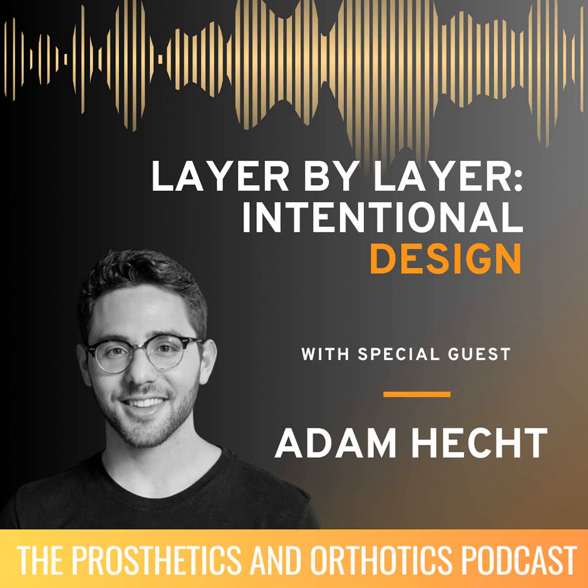Yeah, absolutely. I mean, the Filament Innovations machine is a great starting point. It's almost like a gateway drug to a larger format and printing with pellet. But when you do make that jump there, I would say physics really starts to play a larger role. You're really concerned with gravity. You're really concerned with thermal dissipation as the layers cool and sag, and that does happen with the smaller machines, but almost on a microscopic scale, whereas it's so amplified here. You have to design the tool path as you design the part. I mean, that's just how intertwined they are. It really becomes a huge factor as we design for these larger systems.